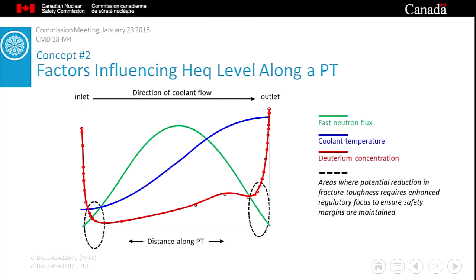The hydrogen equivalent concentration is not uniform over the length of a pressure tube. In this figure, we see a snapshot view of the hydrogen that you would find along a pressure tube as it operates in the reactor. The deuterium pickup, shown in red, is affected by the variation in coolant temperature, which is the blue curve, and the variation in fast neutron flux, which is shown in the green curve, over the length of the tube. The method of installation of the tube at its ends also has an impact on hydrogen pickup.